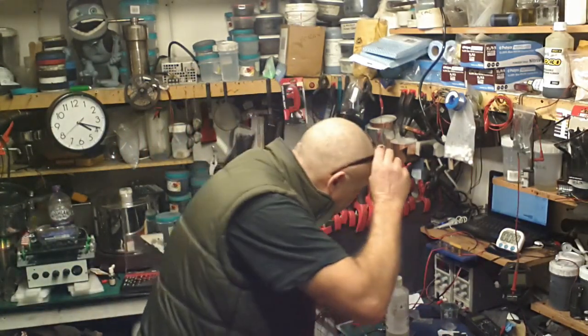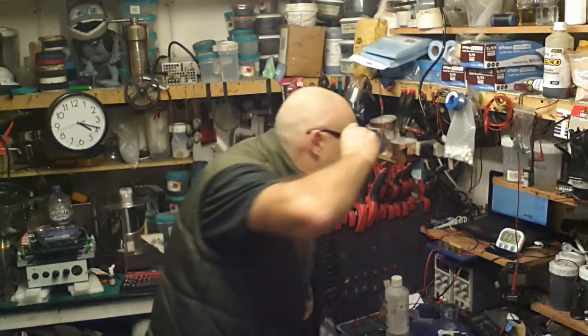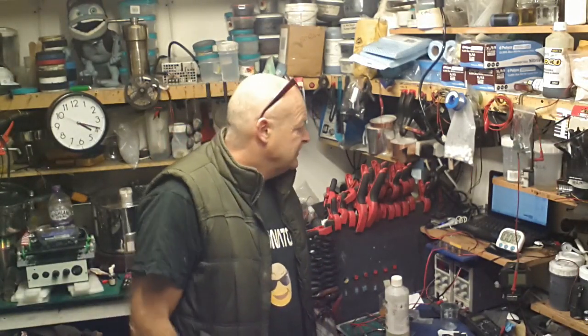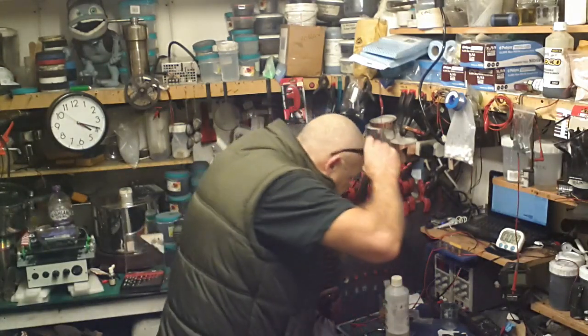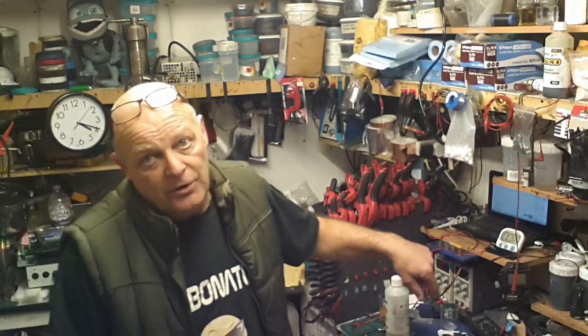This one, yeah, 10 minutes, 0.723 volts left, so it's doing all right. Rest of it, yeah, 4 milliwatt hours, 3 milliamp hours. So it's working. Now I've done a couple of other sheets, so I can do a larger one of these like this with the zinc hexacyanoferrate.